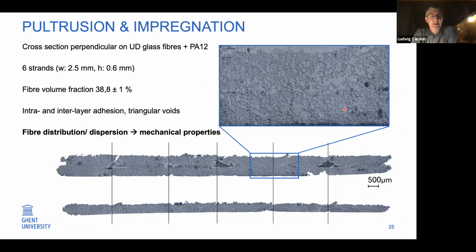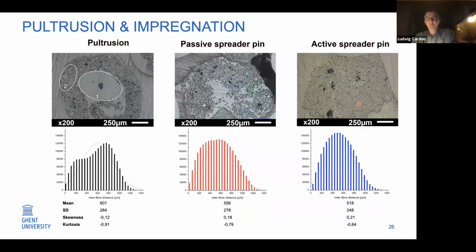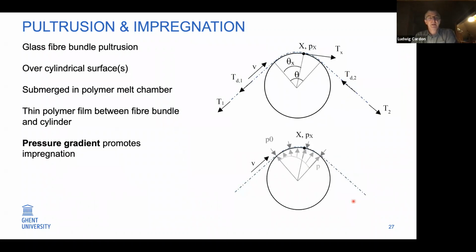I don't have an image immediately on my slides, but when you compare that, for instance, with the Markforged fiber 3D printing, the amount of fiber is a lot less, and also the fiber distribution is really low. So that we also investigate by finding out the distribution of the fibers, which I briefly show here from the pultrusion, the passive pin, and the good distribution of the active pin, spreader pin. So also impregnation is important. So we calculate the angles, the impregnation possibilities for spreading out the fibers.